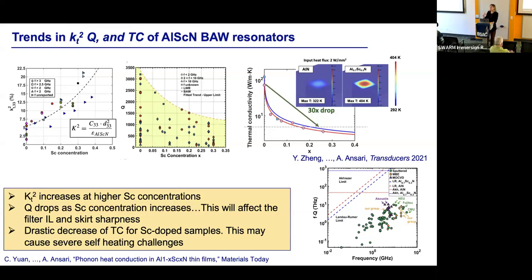So generally, as you add more and more scandium to the lattice, your lattice becomes softer. That's another reason why you can easily switch it up and down, right? So the frequency decreases slightly as you add more and more scandium. I didn't put this here. All of your elastic constant matrix gets lower, so the frequency decreases slightly. But you can account for that by changing the thickness or the pitch of your resonator. So the frequency does decrease, the Q also decreases. The only thing that goes up is the kt squared, or the coupling. Okay. The next question is about the frequency.